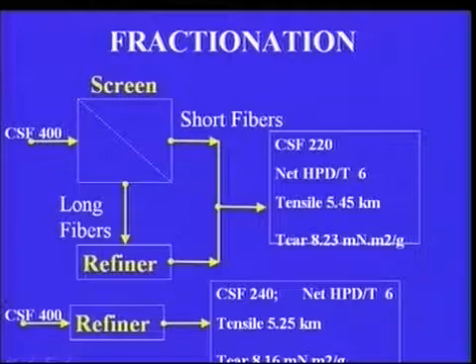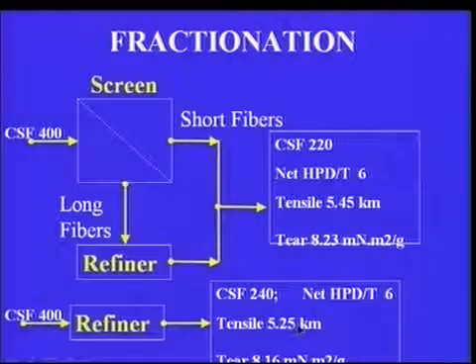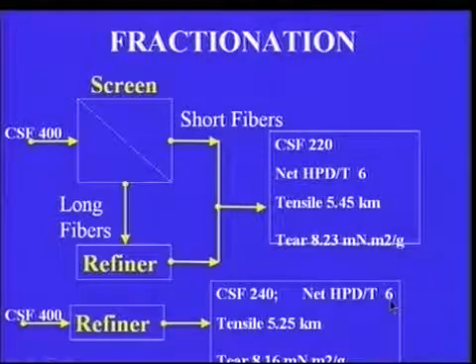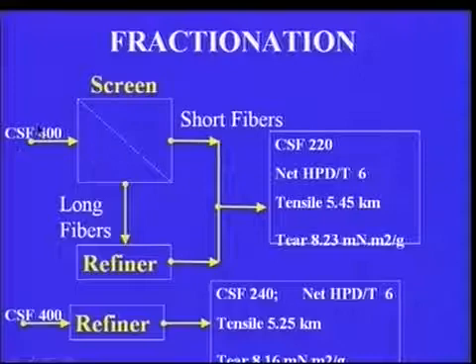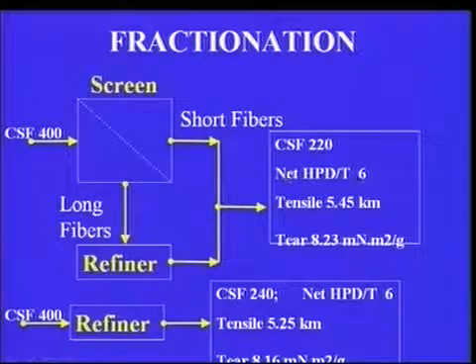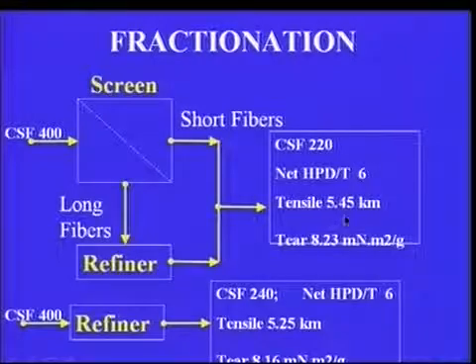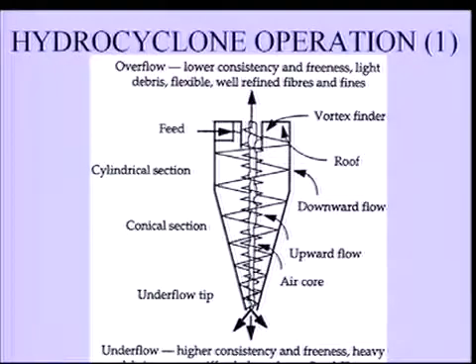Another example is when we have a pulp with the Canadian standard freeness of 400 and refine it to 240 freeness using the net energy of about 6 horsepower day per ton, giving you a tensile strength of 5.25 km and tear factor of 8.16. Again, if I go through fractionation and refine only the long fibers to the final freeness of 220 using the same energy consumption, my tensile strength is now 5.45 and tear factor is 8.23. So small benefit of refining separately the long fibers. Another way to fractionate is by using hydrocyclones.